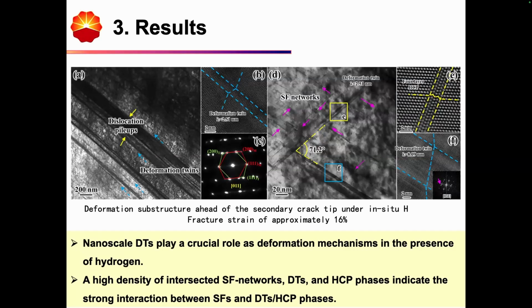Therefore we can see extensive deformation twins located ahead of the crack tip, and some dislocation pile-ups are also observed between the deformation twins.